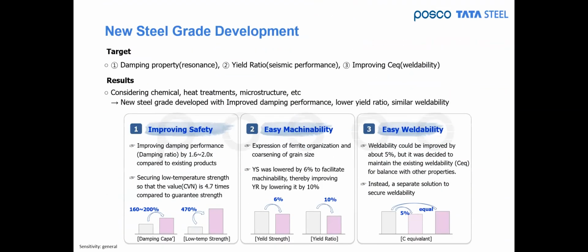And then from those 3 topics, if we come back to the steel side, it comes down to where damping property was chosen, then yield ratio for better, easier machinability, and then improving CEQs for the weldability. So considering the different chemical compositions, heat treatments, or microstructures, a new steel grade was developed with improved damping performance, lower yield ratio and similar weldability.